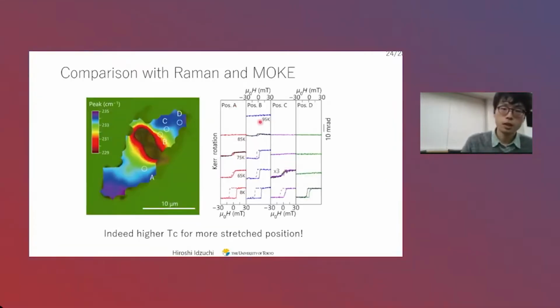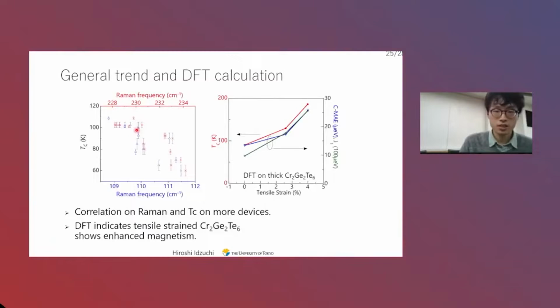And we have some correlation with Raman and Tc. So if we have more stretch, somehow we have a higher Curie temperature. That's what we have seen. And we see more device characteristics that are basically the same thing, but for more devices. And then DFT calculation was done for thicker CGT instead of the monolayer CGT reported. And also with tensile strain, we see enhanced magnetism, either magnetic anisotropy by crystal, or exchange energy, or even Curie temperature.